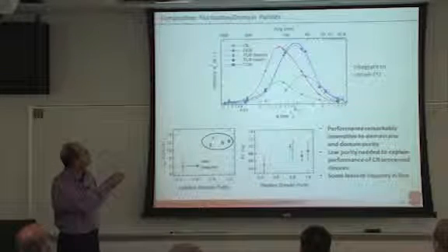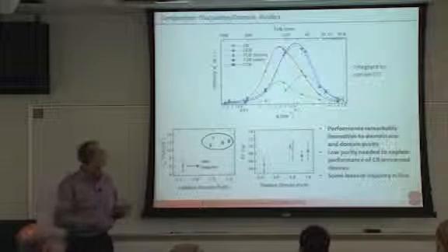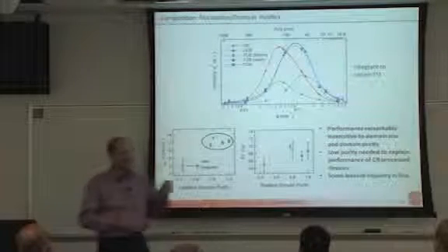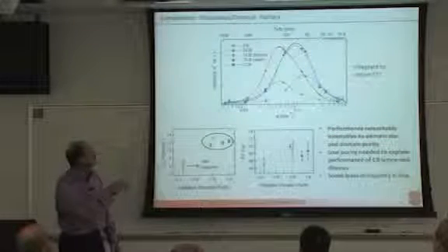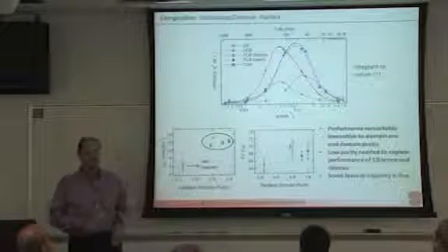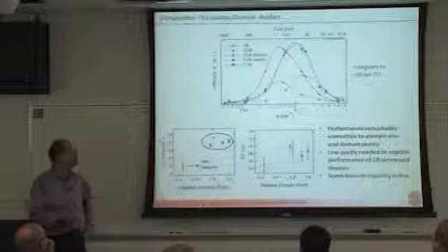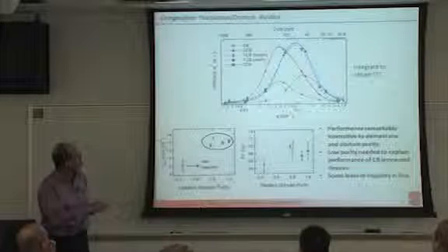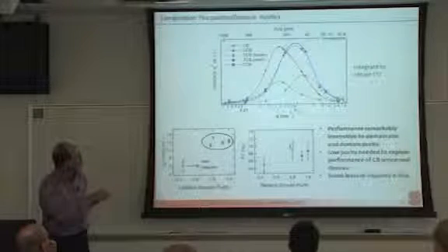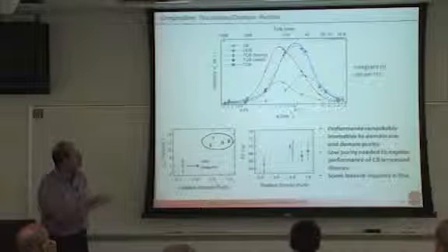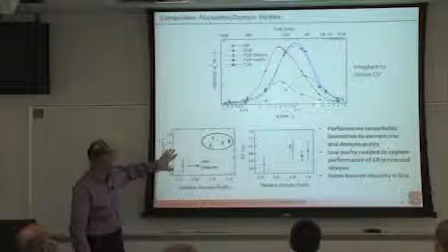So here we have 3 different solvents, and frozen, short and long annealed. For the trichlorobenzene, frozen means they immediately take it and put it in a vacuum. And short is where they put a Petri dish on top of it, and the residual solvent gives you a bit of solvent annealing. And so we get these resonant scattering curves that give me different domain size distributions. I can integrate that. That gives me the composition fluctuations, so I can again look at that.